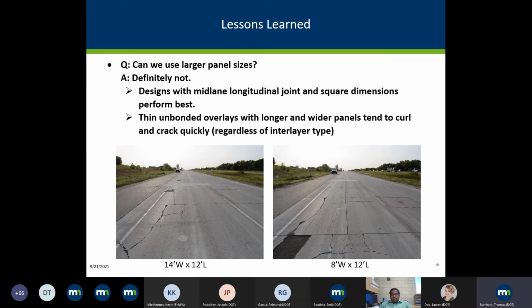Can we use larger panel size? And I agree with Manik, definitely not. Whether they had fibers or not, these thin, large panel overlays, I believe they curl too much. And this is what you get: no matter how you slice and dice the panel size, if it's too large, it's going to crack.